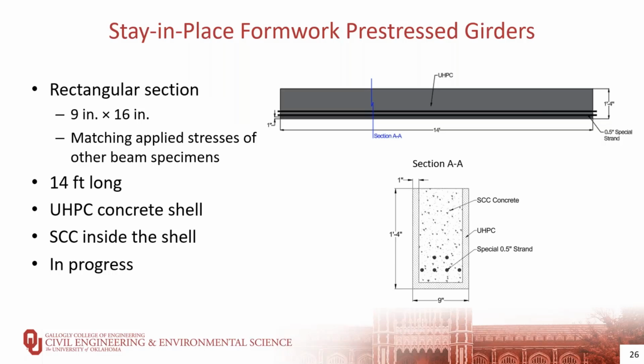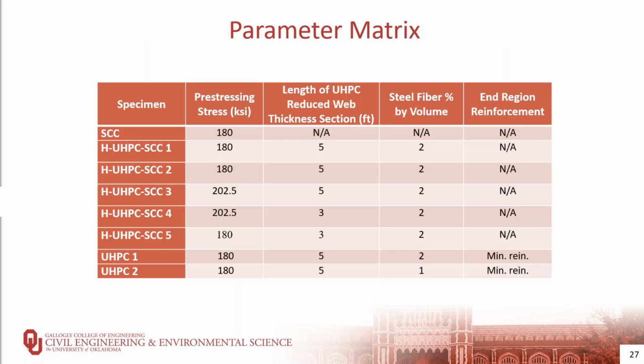For the stay-in-place formwork pre-stressed girders, the cross section was changed to a 9-inch by 16-inch rectangular section, as shown in section AA on the bottom figure on the right, to simplify the form construction for this proof of concept. The dimensions were selected to match the applied stresses of the other beam specimens with the same number of strands and locations. The length of this type of girder is 14 feet, not 18 feet, similar to the UHPC girders. The design has been finalized, but we haven't started construction of these specimens at this point. Here's the parameter matrix for the specimens that have been cast already.